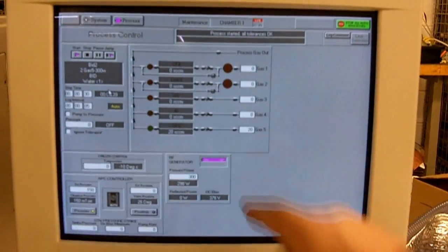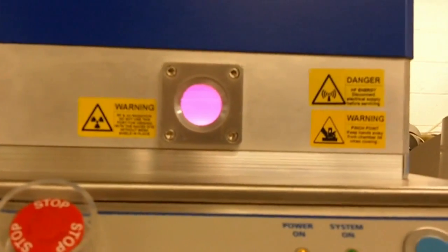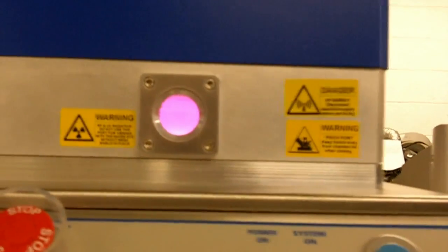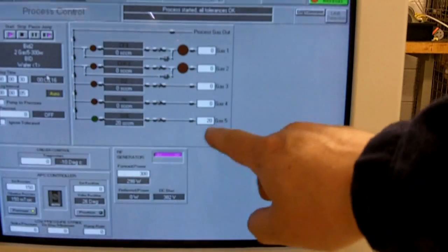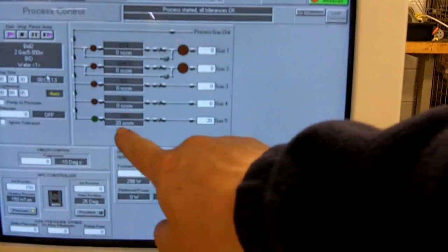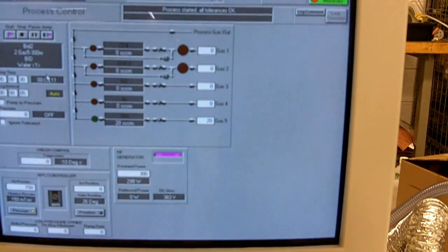So once you see the light coming on here, you can see that you have plasma in there and it's running at 300 watts. Let me put you back over to the screen and you can see that it's at 300 watts at zero reflective. Gas 5's at 20 SCCM, which is indicated right here. Your mass flow is working correctly, and your gas pressure is at 150 millitorr in the chamber. It is running for 30 seconds, and you can see it's just about ready to time out right where the arrow's at. So then it's going to go to gas 4 at 40 SCCM